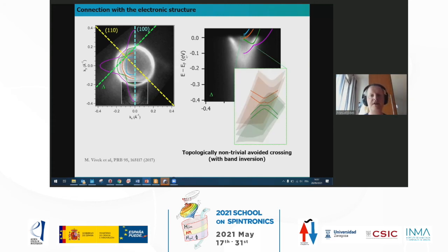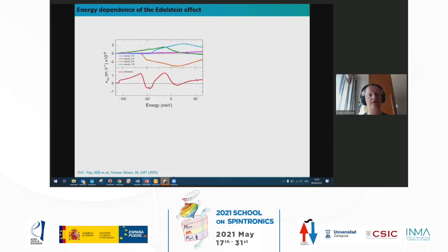And this gives a very rich physics. And from theory, we can calculate that here we have a topologically non-trivial crossing, a little bit like what happens in topological insulators. So we expect that when the Fermi level is going to sit there, we're going to have a larger spin-to-charge conversion. So our colleagues from Halle computed, using these band calculations, the efficiency of the spin-to-charge conversion for each pair of bands that I've shown you, and then this is the sum.